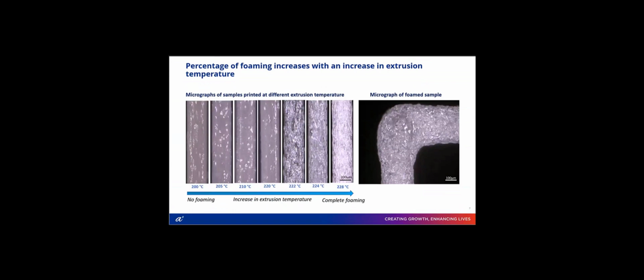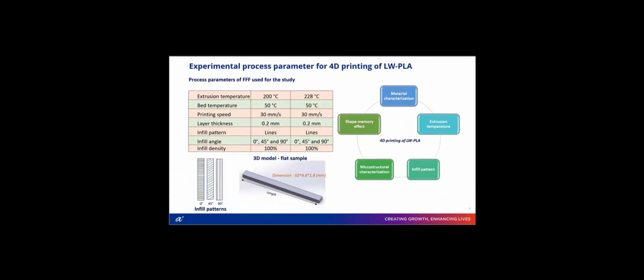To understand further how this extrusion temperature affects the foaming process, the single wall perimeter cubes were observed under microscopy for the foaming pattern. We could see the increase in percentage of foaming from the lower extrusion temperature to higher extrusion temperature. And it is very visible in the micrograph that the pores are formed when we see the sample printed at 228 degrees Celsius.